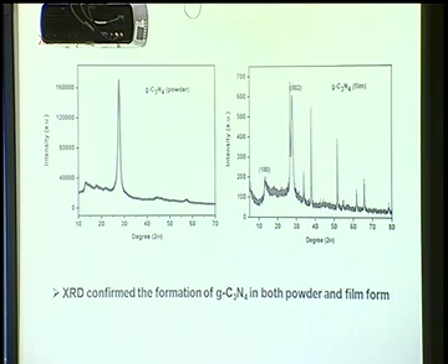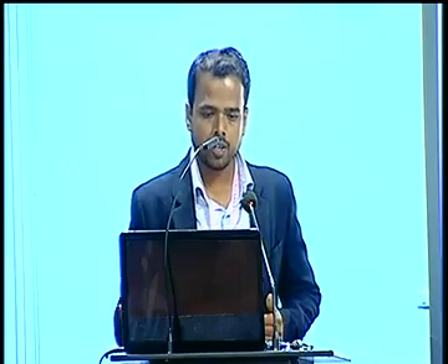in a crucible, and I put an FTO plate. The FTO surface is the conductive surface, so it is faced towards the sample. When I heated it at 550 degrees centigrade for 2 hours, I could successfully synthesize the thin film in only a single step. I have characterized this material by XRD, and the XRD showed that the material is successfully prepared, both as powder and as thin film. The 002 peak is due to the interlayer distance in graphite carbon nitride, and the 100 plane is due to the hole-to-hole distance in the tri-s-triazine unit plane of the graphite carbon nitride.